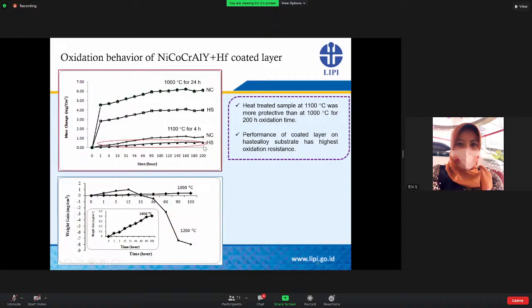Based on the microstructure and the microhardness, samples were subjected to higher temperature oxidation, 1200 degrees C. This figure shows that the weight gain of the sample oxidized at 1000 degrees C is slower than that of the sample oxidized at 1200 degrees C. The oxidation kinetics of the sample oxidized at 1000 degrees C follow parabolic rate laws.